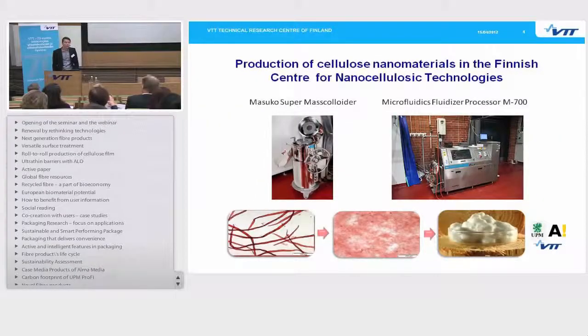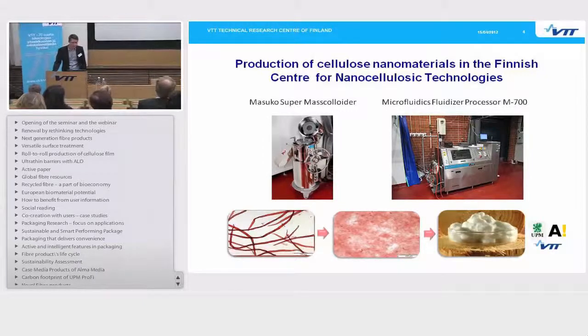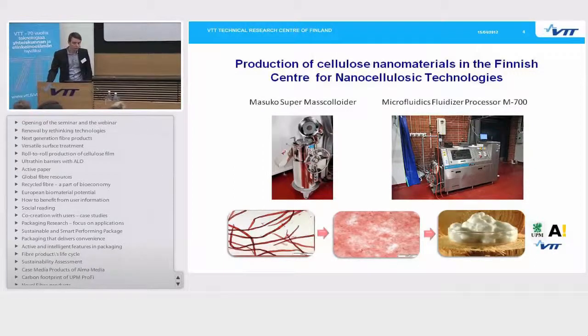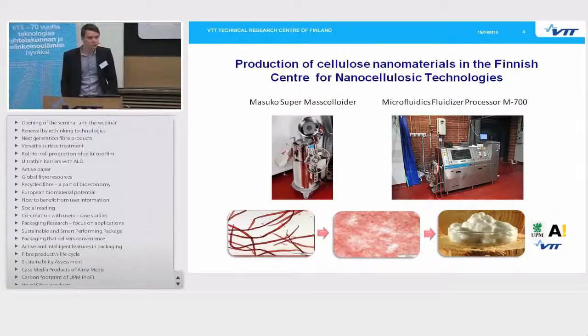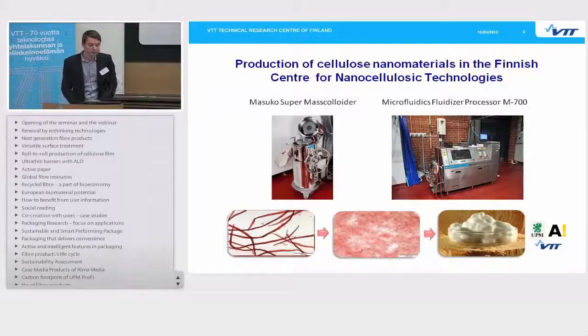We have two types of equipment we are now using to make our nanocellulose material. Both are based on mechanical methods. The first is called the Masuko Super Masscolloider, and the other is called the Microfluidics Fluidizer. The basic principle of the Masuko Grinder is that there are two grinding stones — one rotating and one stationary — and we force fibers through the gap between the stones. When we do this enough, the fibers are ground down to the nanoscale.